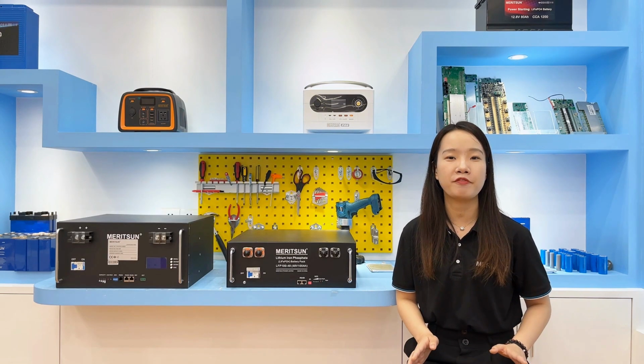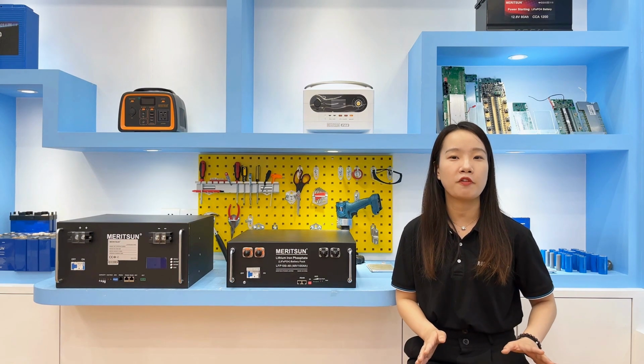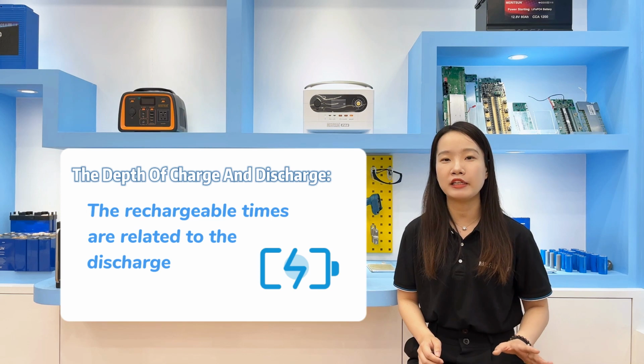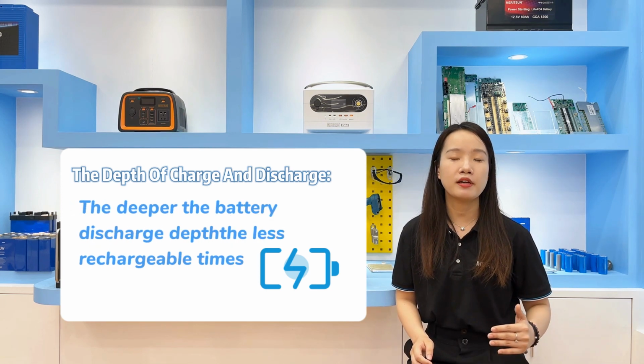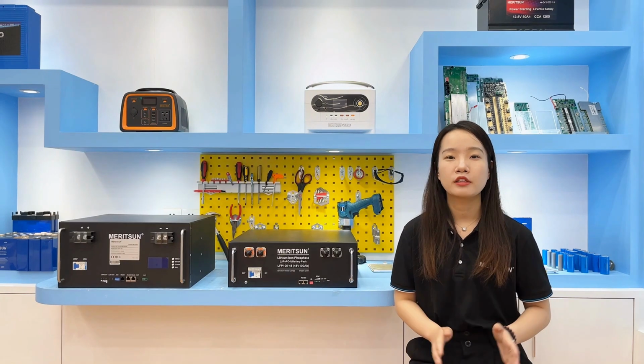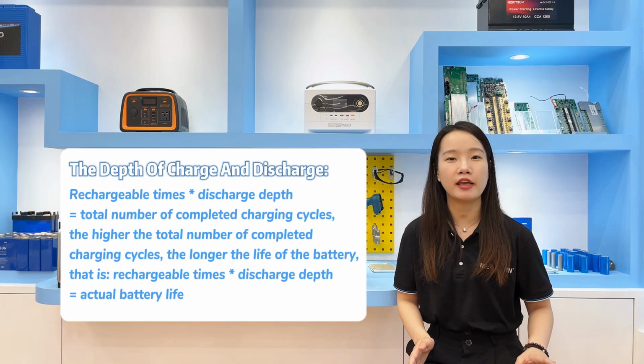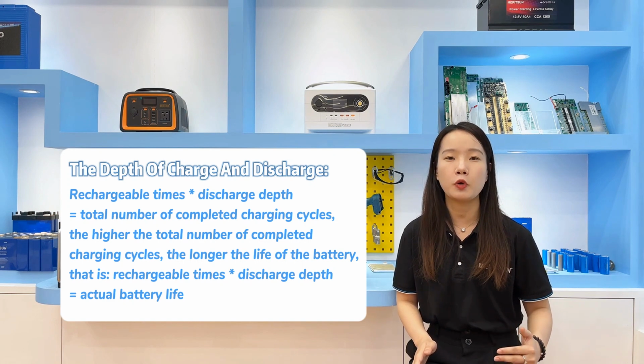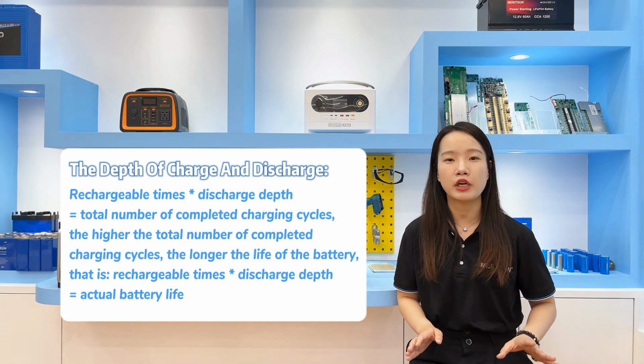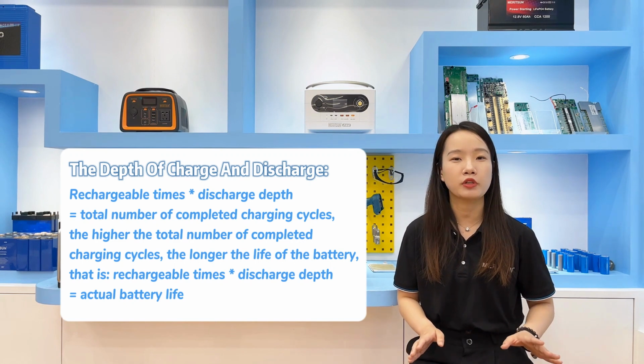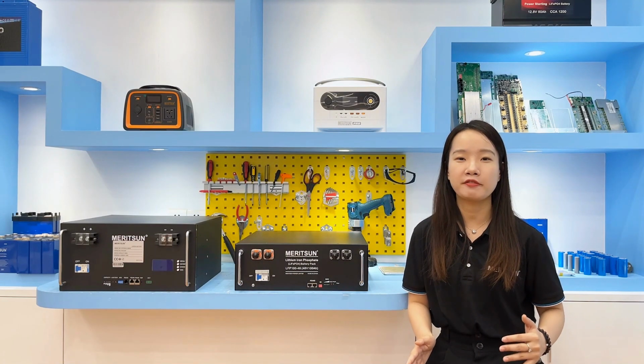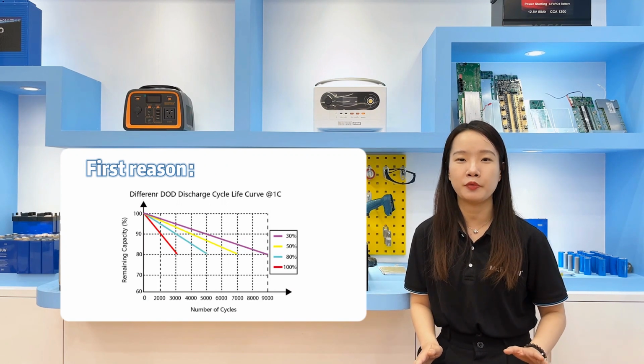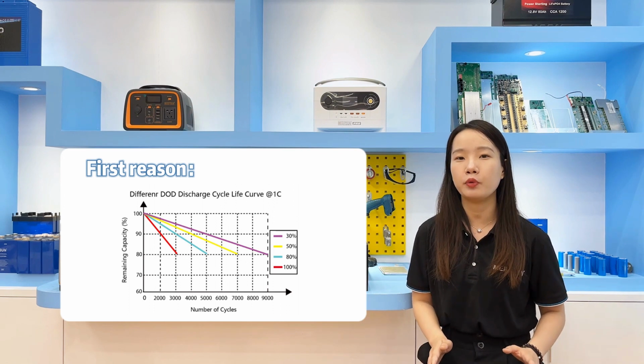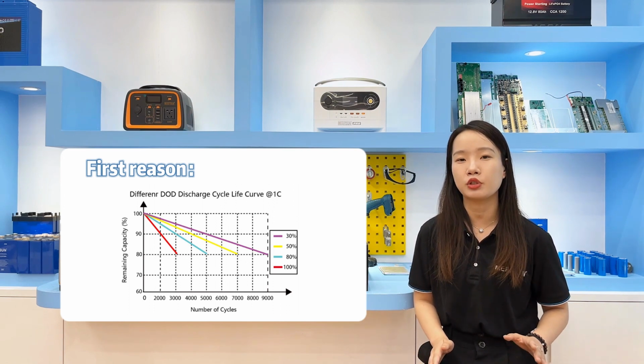So let's talk about another main factor affecting the battery life, that is the depth of charge and discharge. The rechargeable times are related to the depth of discharge, that is, the deeper the battery discharge, the fewer rechargeable times. The rechargeable times multiplied by the discharge depth equal the total number of complete charge cycles. The higher the total number of complete charge cycles, the longer the life of the batteries. Among them, the impact of depth of discharge is greater than the depth of charge. The first reason is that the cycle life increases sharply with the decrease of the depth of discharge. From the curve table, you can see the cycle life times of different depths of discharge compared.